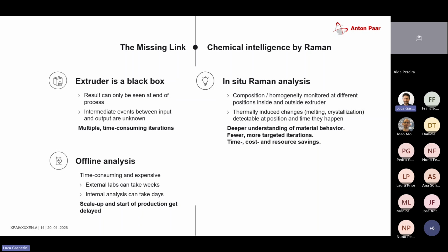The main issue is how homogeneous your sample is. If it's very heterogeneous, like at the start of the reaction, then you typically would not see much. But at a later point where it gets homogeneous, then you would get the most information out of it. But here we are in small conditions, with a bit that is immersed. But for example, in the big reactor, things will be scaled up. Yes, I mean, the thing is, it's a single point, like you have a focus point of 600 nanometer range, on an area.